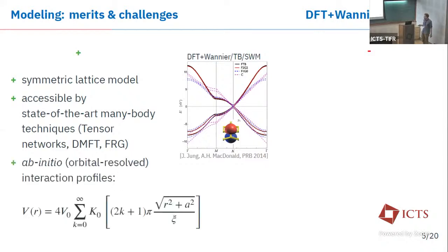And last but not least, you have the possibility to write down ab initio motivated interaction profiles. So this would be an example of a dual-gated Coulomb interaction that is both screened long and short range. And it's very easy to write that down in real space for a tight binding model. You can even go ahead and project some actual 1/r to your Wannier functions you get out from DFT plus Wannierization. So you have all the power of actually taking your actual realistic Coulomb interaction and seeing what it boils down to in the effective model.